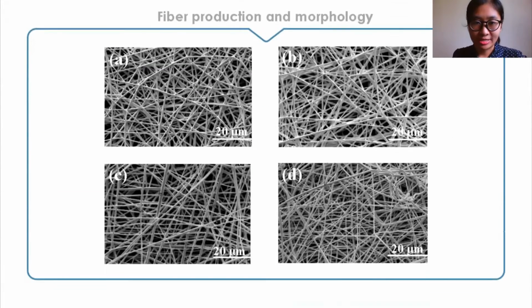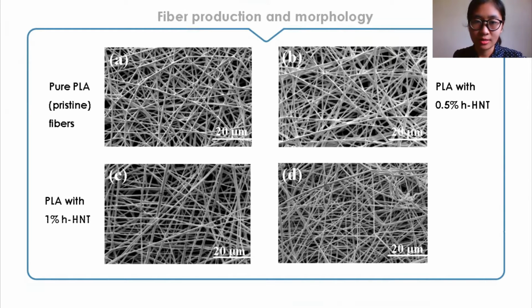Moving on to the characterization of fiber mats, looking more closely using a scanning electron microscope, results show thin bead-free fiber structures in randomly oriented formations. So the production of PLA fibers was obtained at 12%, which was also used as the basis for clay content. Varying concentrations of hydroxylated halloysite were successfully electrospun into fiber mats.